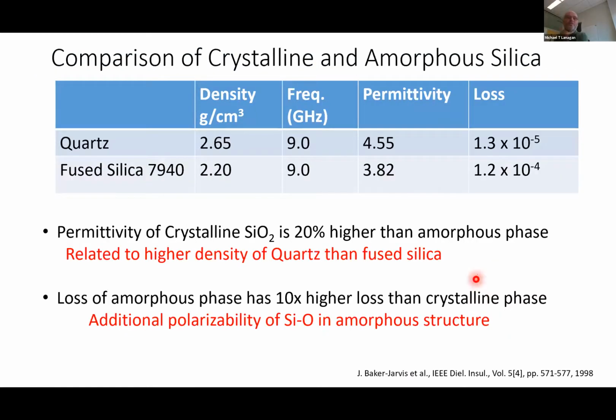All right, so if we do a comparison of crystalline and amorphous silicon oxide, both are the same chemically, they're both SiO2. And as we compare the response at say 9 gigahertz, we can see the permittivity values are here, but we have an order of magnitude difference in this loss, and loss becomes very important for a lot of these applications. And what is causing this higher loss for the same chemistry? So that was our big question, and it really is related to structure.